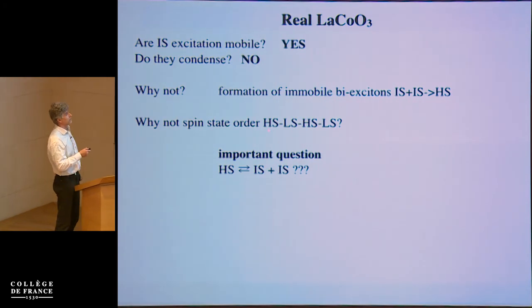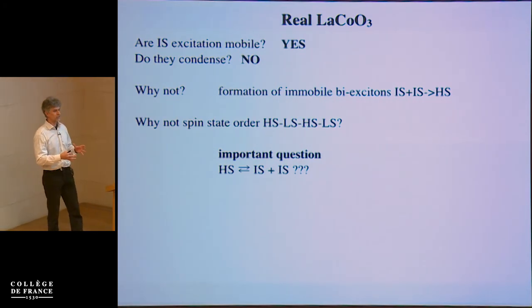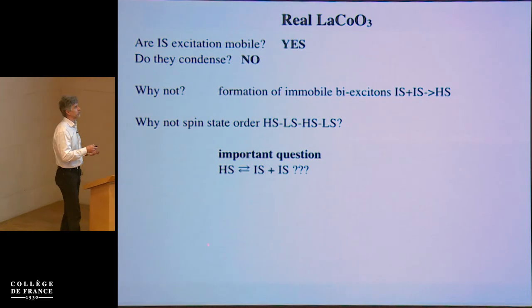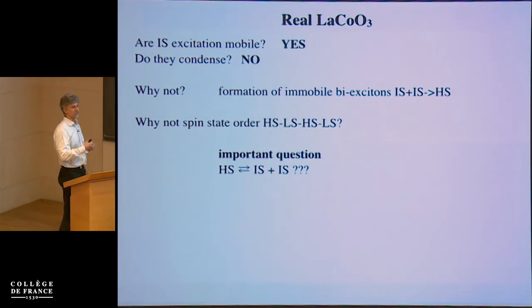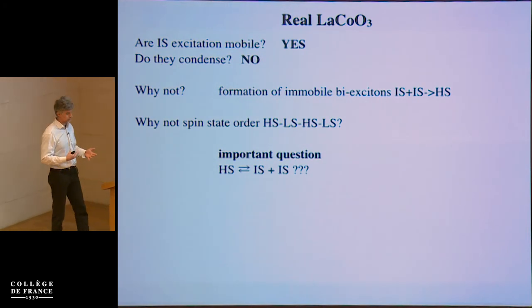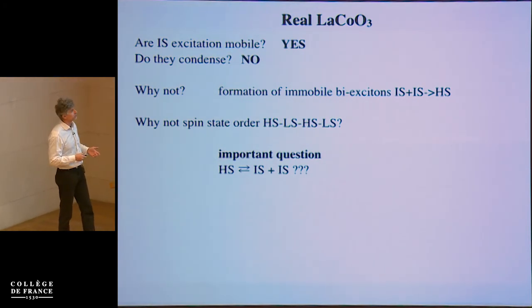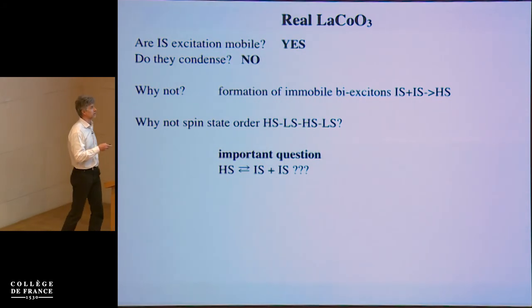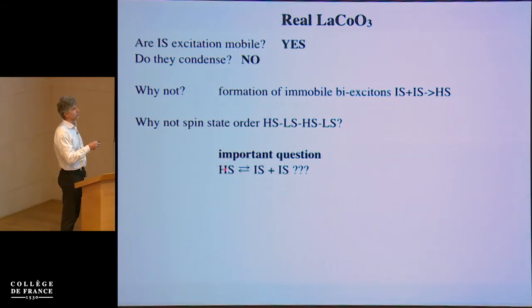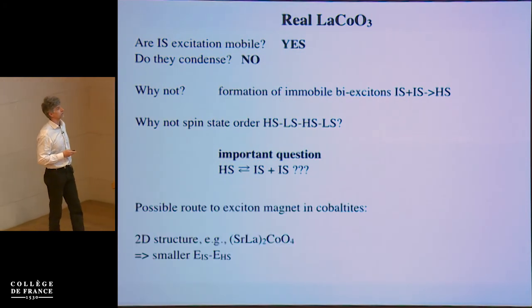This kind of interaction would probably hinder the excitonic condensation. On the other hand, if the intermediate spin states were not present, the obvious question would be, why don't we observe high spin, low spin, high spin, low spin order, which is expected theoretically? My personal suggestion is that it is the presence of these fluctuations: the high spin is not really an atomic-like excitation, but is a high spin dressed with fluctuations of intermediate spins. That is the answer to the question.